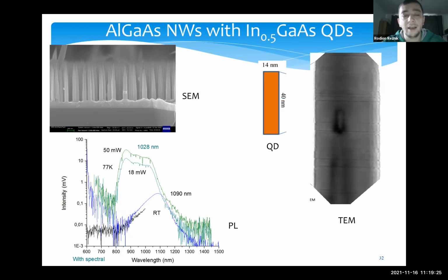Also, the stress affects the energy of radiation, like colleagues have shown in their publications. So we will have the shift of photoluminescence, as I remember, it depends on which material's lattice parameter is bigger. So in this case, as I remember, we will have a shift to high energies. Okay, thank you.